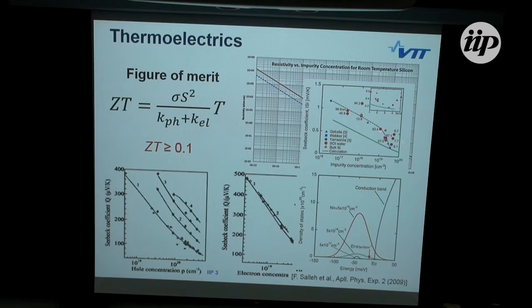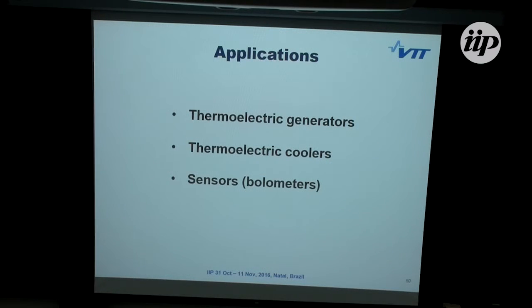Then there was one paper, which has not been proven by any other group, that comes from Japan. They claim that when the doping density is close to 10 to 20, the Seebeck coefficient starts to increase already. If this is true, then this number can be even higher. So, three examples: a thermoelectric generator or cooler, and then, maybe more interesting, sensors or bolometers.